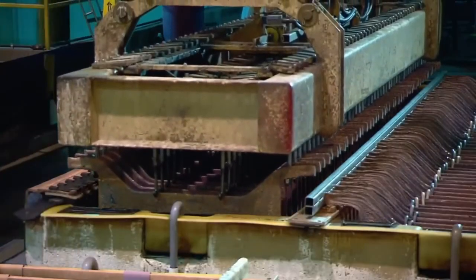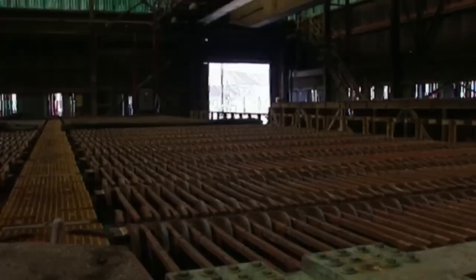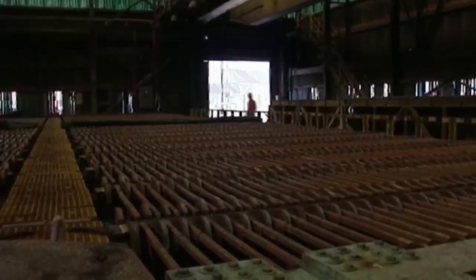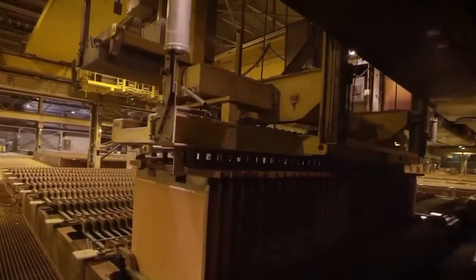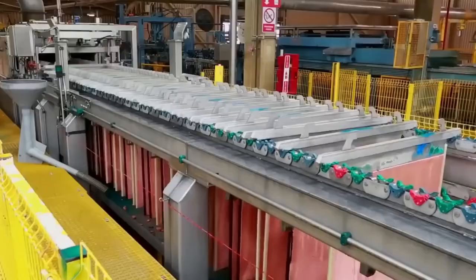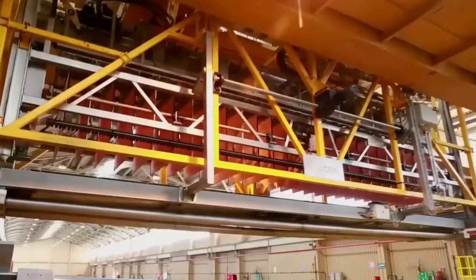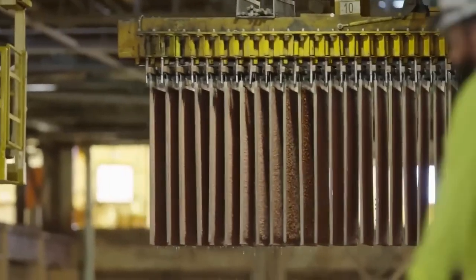The anodes are immersed in electrolyte tanks opposite thin metal sheets called cathodes. When an electric current is applied, pure copper transfers from the anodes to the cathodes, while impurities fall to the bottom of the tank. The result is 99.99% pure copper, suitable for making the most demanding electrical cables.